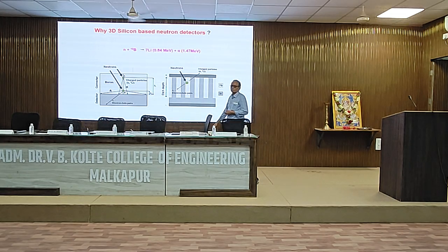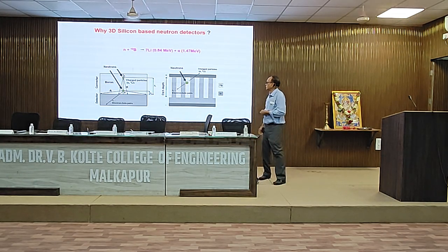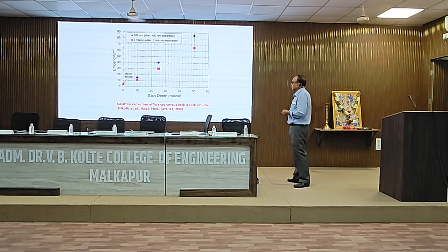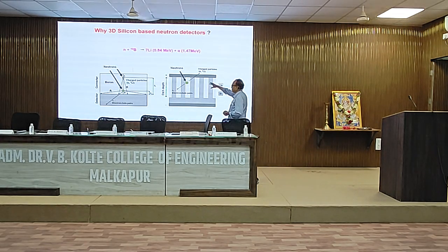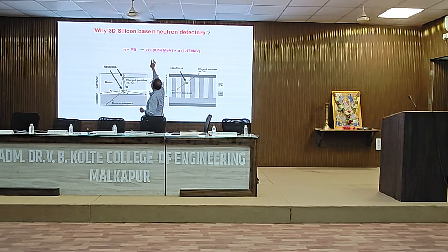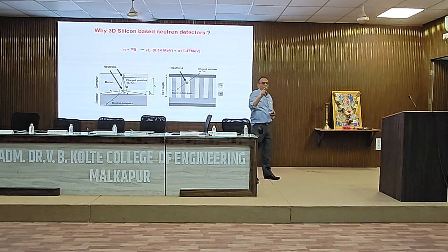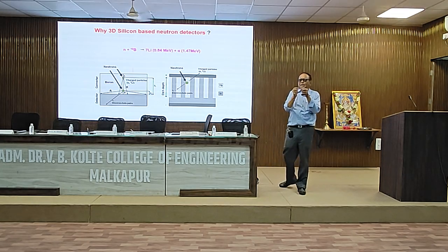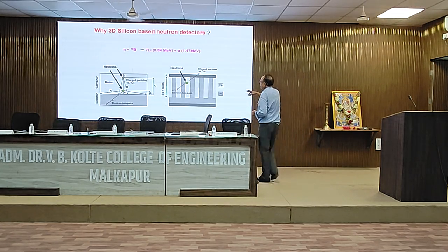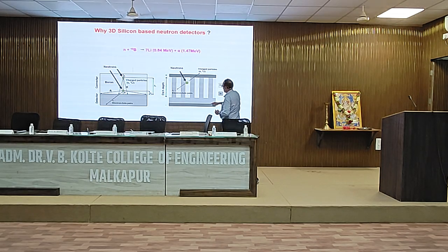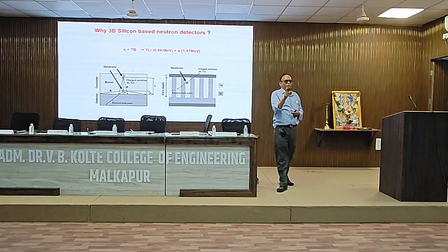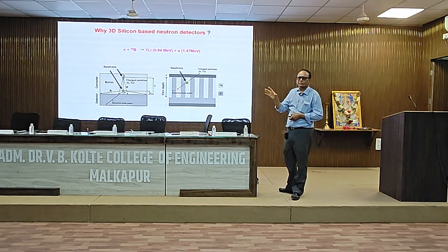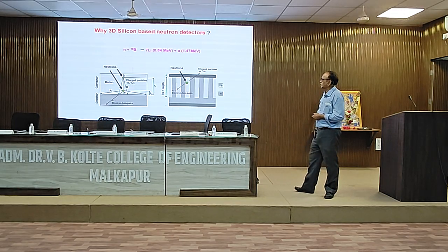Again, this boron carbide is filled through chemical vapor deposition during the plasma process. Once you fill it into these trenches, it has boron 10, which interacts with your neutron and gives you lithium and an alpha particle. The alpha particle, being energetic, generates electron-ion pairs in that p-i-n junction. These electron-ion pairs are then attracted across this electrode and this electrode, and you get the pulse. Each neutron that encounters boron 10 gives a pulse, so you can detect the presence of the neutron emitter in that region.